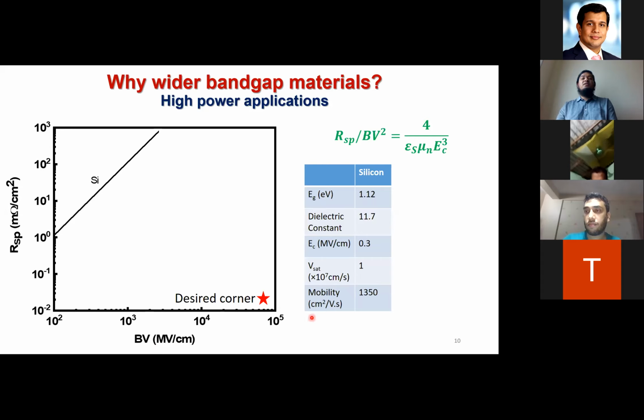And if we take the parameters for silicon from the literature and plot, we'll get a curve like this. And just to remind you, our goal is to move to this corner on the bottom right, where we have the highest possible blocking voltage and the lowest possible on-resistance. So this clearly shows that the application of the silicon transistor, just from a material point of view, is very limited, below 1000 volts in this range. We cannot cross beyond this line because of material parameter limitation.